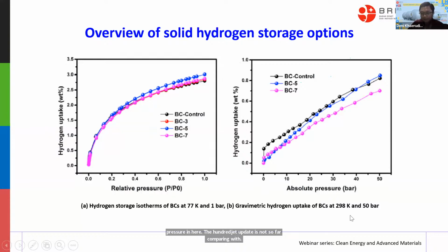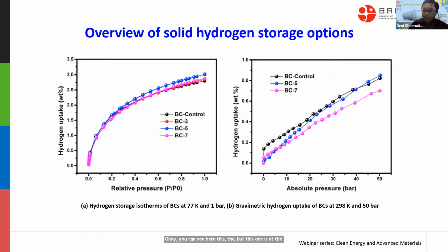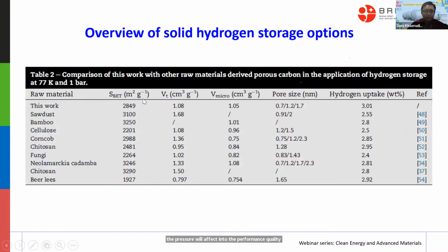Okay, you can see here this is B. This one is at the condition 298 Kelvin, about 27 degrees C, and the pressure is up to 50 bar. Meanwhile, on the left side is 77 Kelvin. This is the liquid nitrogen state, meaning about minus 200 degrees C. And this is at 1 bar. So for sure, the temperature and also the pressure will affect the quality of hydrogen storage performance in materials. Yeah, this is the result of their work.